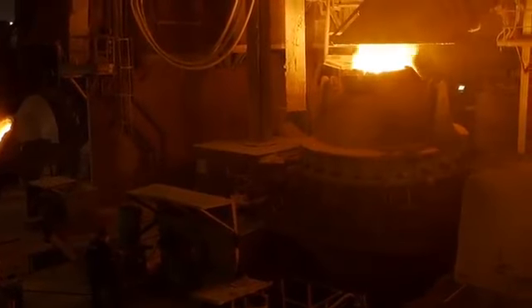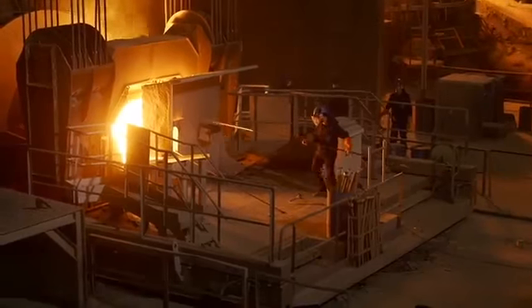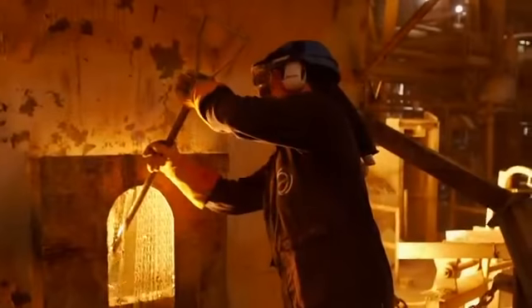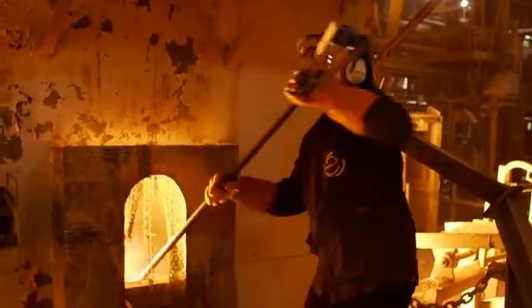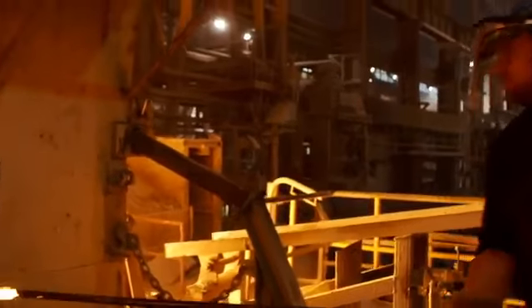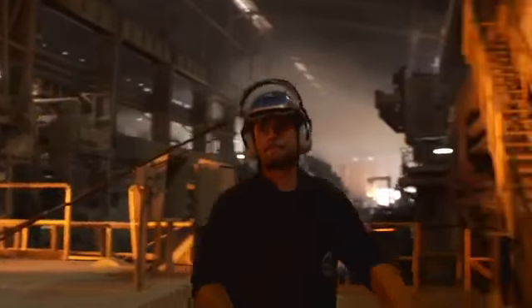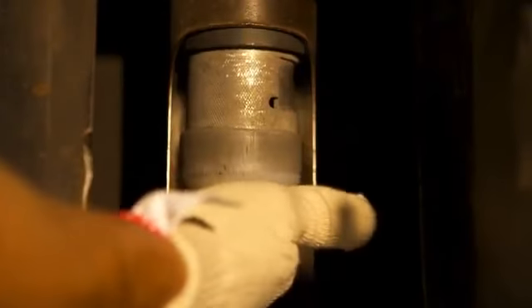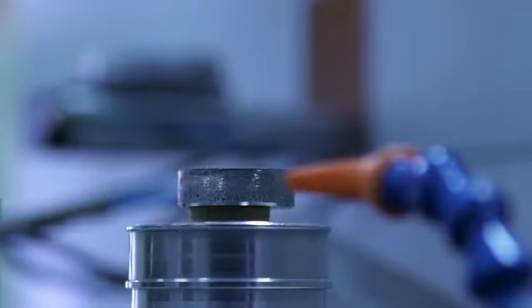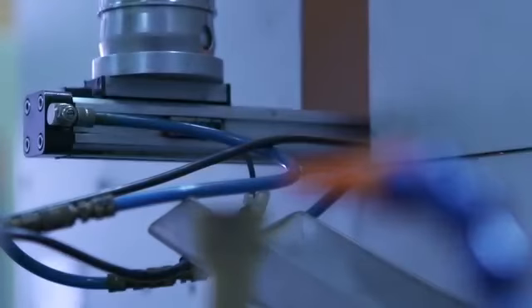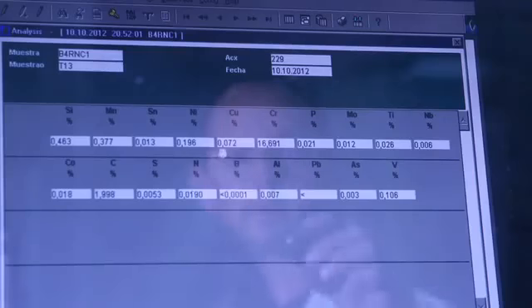The main process steps in the AOD are decarburation, where the carbon content of the melt is minimized. Reduction, recovering metal from the metallic oxides. And desulfurization, where the sulfur content is reduced. In the final stage, small additions of high-quality raw material can be made. During the process, samples are taken, and the chemical composition is analyzed in real time in the adjoining laboratory in order to fine-tune the elements to be added.